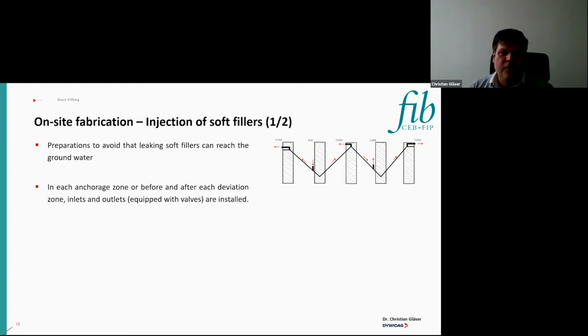Just some thoughts here about the way of the injection. Of course, especially in case of soft fillers, we need to make preparations to avoid that leaking soft fillers can reach the groundwater. So that might be an important thing to consider quite early in the job site planning. Typically all anchorage zones and all deviation areas need to have inlets and outlets to allow a proper injection. So you see in the sketch on the right-hand side that you need at least one inlet, and at all high points, anchorages, and so on, outlets are also required.